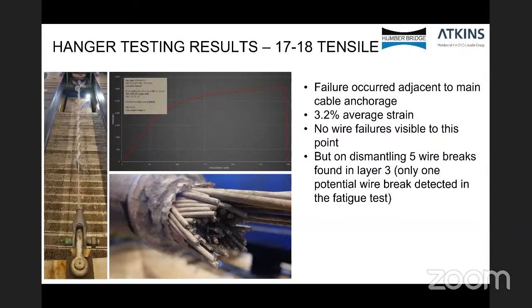This just goes through where the wire broke. It was towards the top socket where there was less lubrication because of the inclination of the hanger. There was also some more corrosion damage. On dismounting of the wires, we found that on layer 3, there was one potential wire break detected in the fatigue testing. The mode of failure for each individual wire was a ductile failure. And we didn't see, in this instance, a brittle failure of the wires. So we go on to the next hanger.